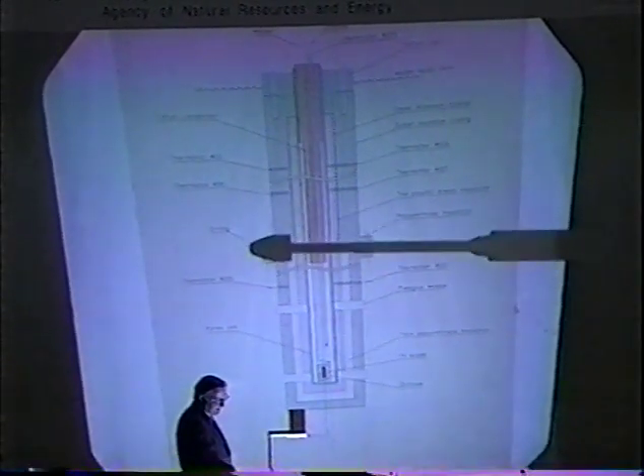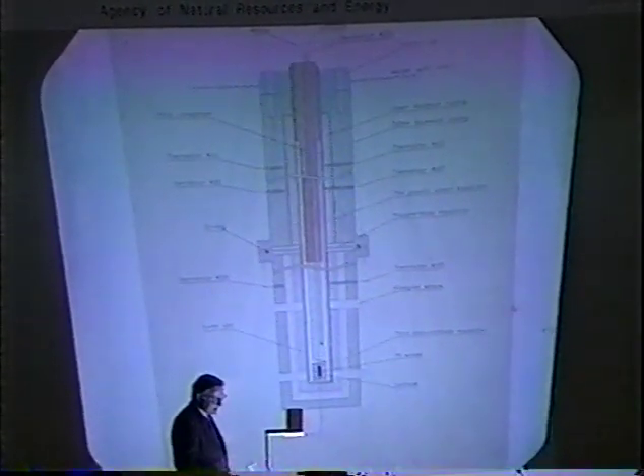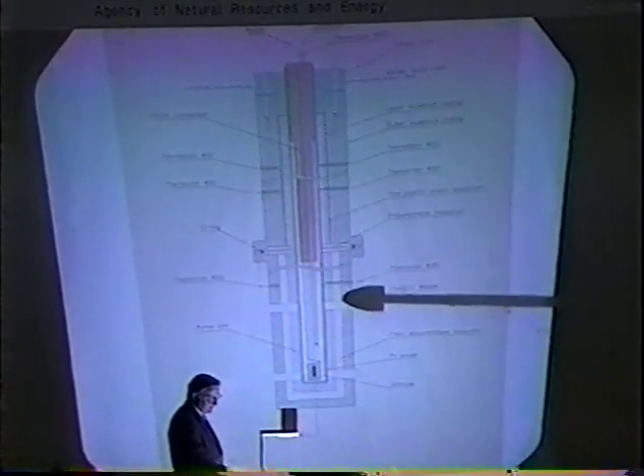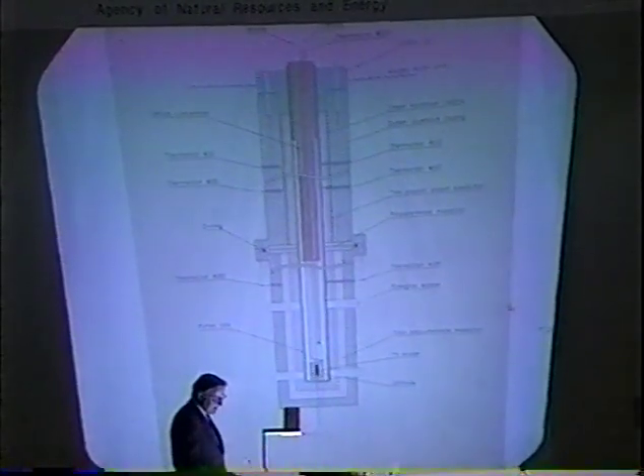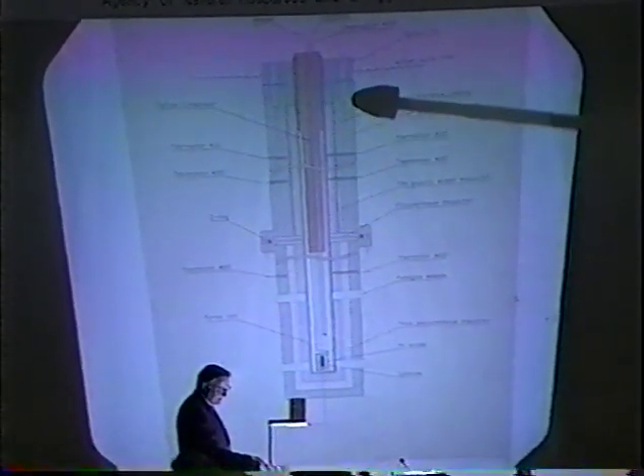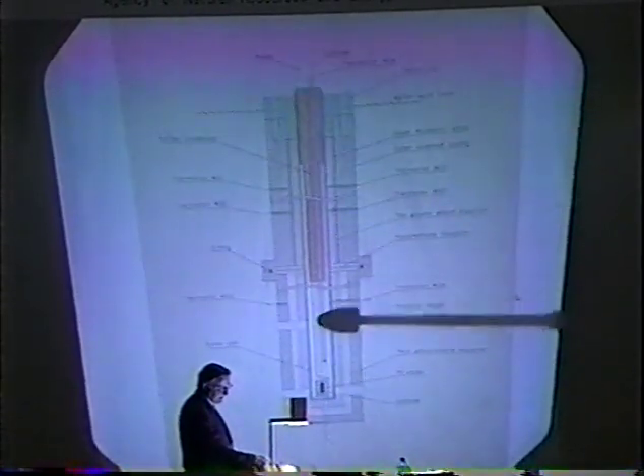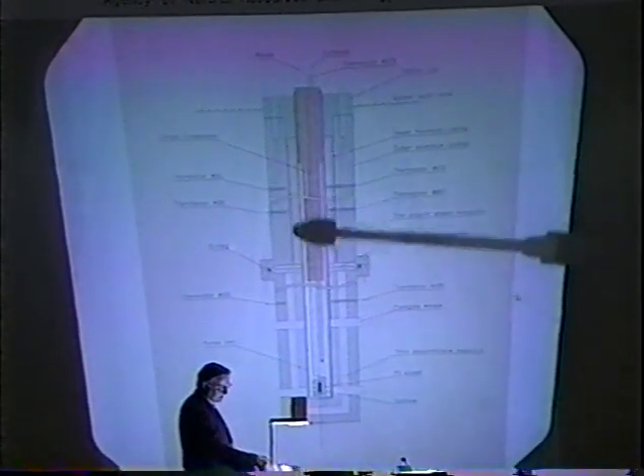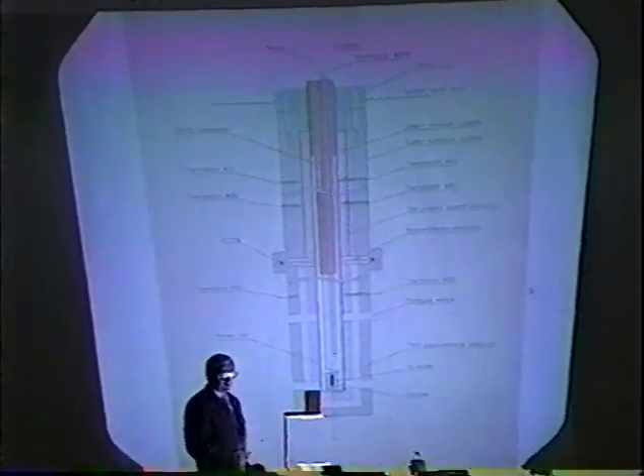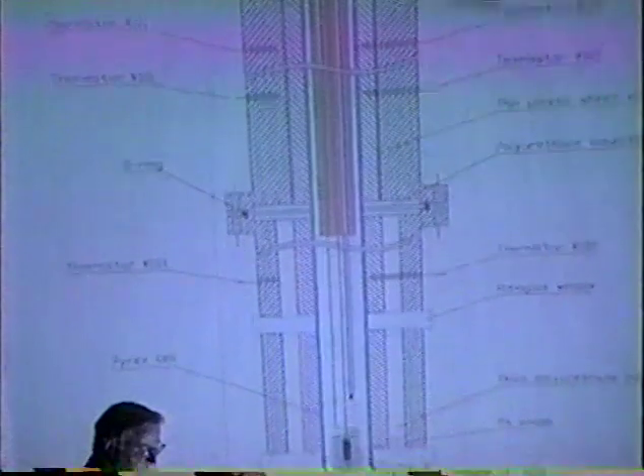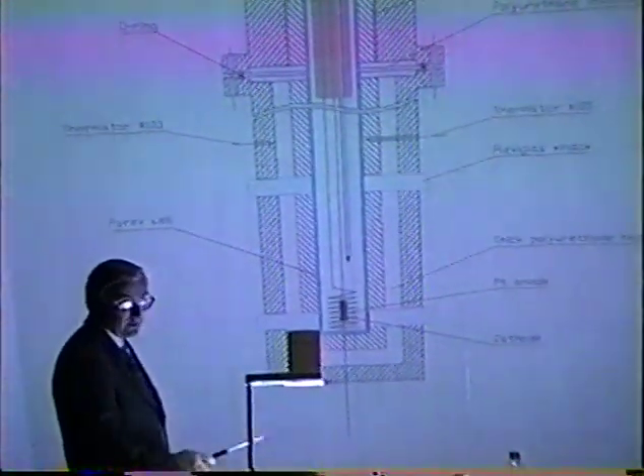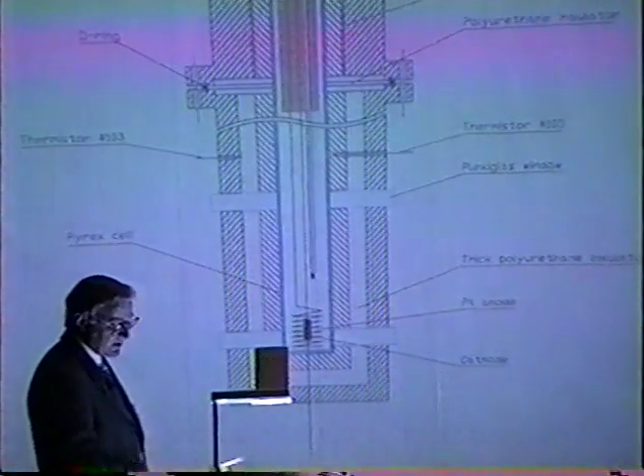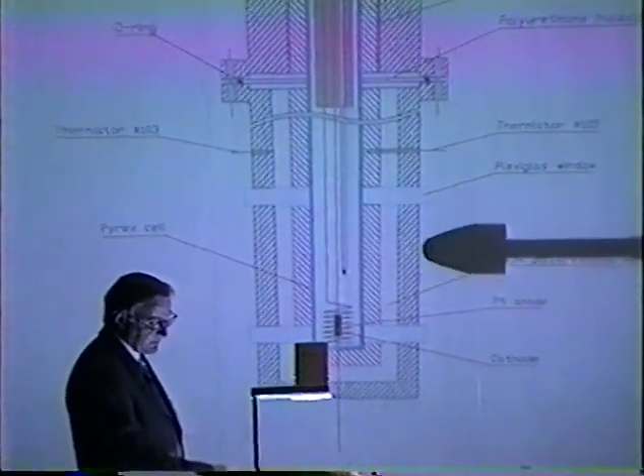It's divided into two sections. The lower section, which we will call the reaction section, is more heavily insulated on the interior. The insulation is this white area. The glass or quartz cell is held in the center. That is in close thermal contact with an aluminum jacket or a steel jacket or a metallic jacket, and separating that inner jacket from the outer casing is an insulating material. So you can change the thickness or the quality of the material in this insulator gap. You can change the thicknesses of the inner and outer metal layers.